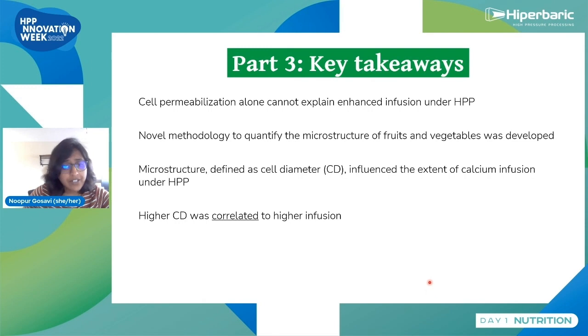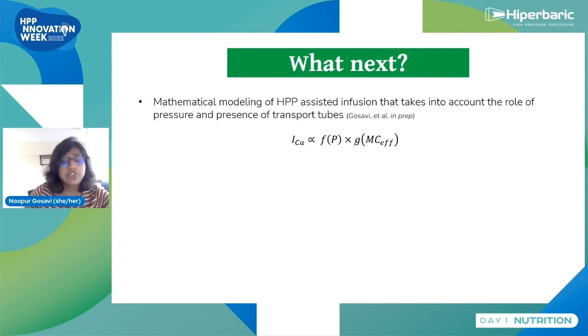So the takeaway here is that cell permeabilization or cell breakage is not enough to explain high pressure infusion, but what is important is the microstructure and how the cell size differs. We showed that high cell diameter correlated to higher infusion, and we developed a methodology to quantify the microstructure of fruits and vegetables. So now what is important is to understand that this is not the end of the story, this is just the beginning.